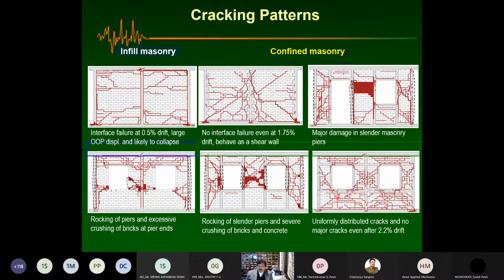What we did in our study is that we keep this continuous, and tie columns don't have to be continuous, but of course they must run around so that they stiffen this opening. Okay, so this is the system difference, and now you can see that this performs much better than this. So we know that these horizontal bands are necessary, and the only thing we have to do is to construct them in such a way that the masonry is done first, and then these tie elements are cast later. Okay, and this is again the Latin American practice. So openings are large, this is large slender masonry, but had this been continuous, probably the deformations would be much smaller. I did not show you the videos of these tests.